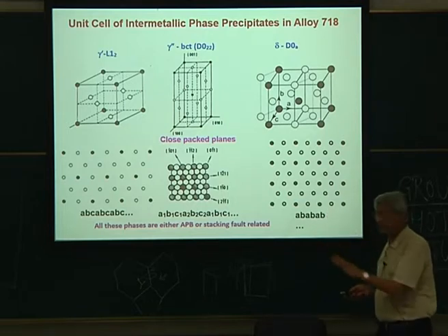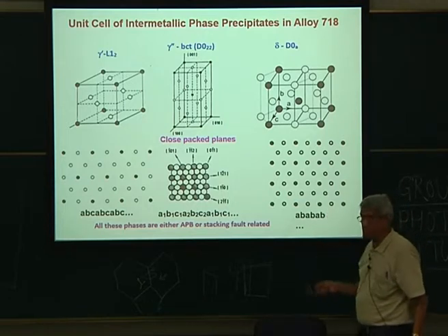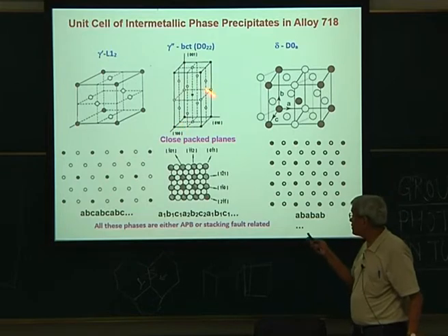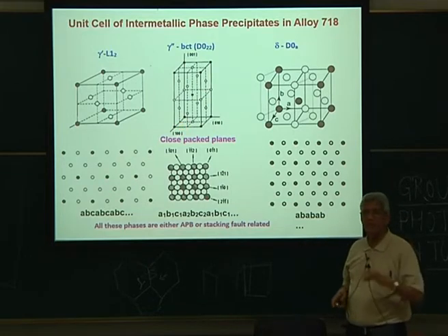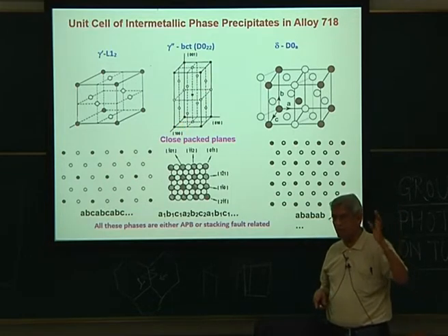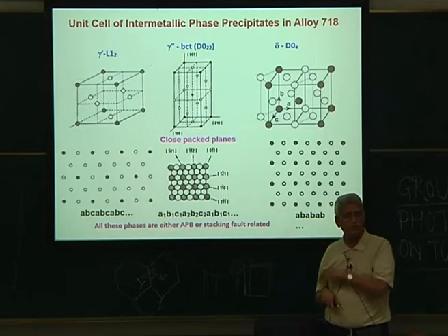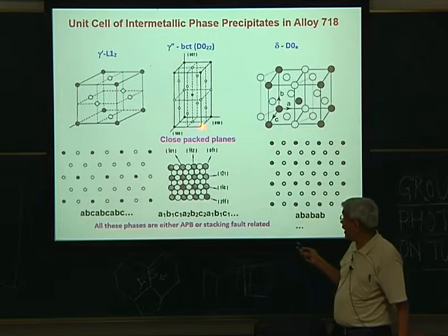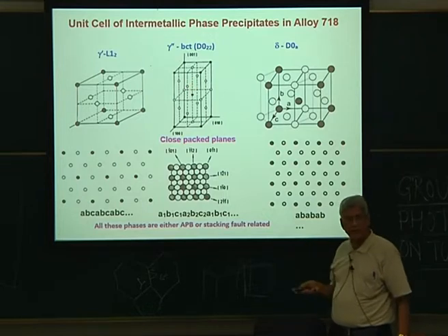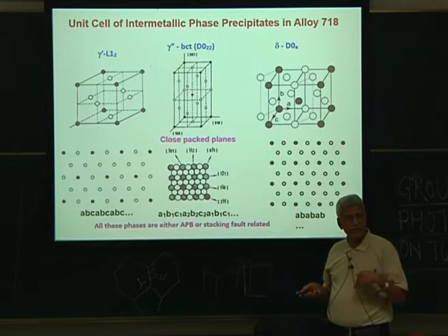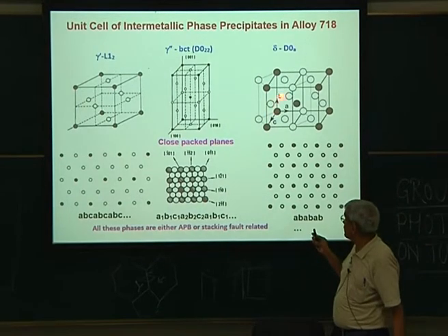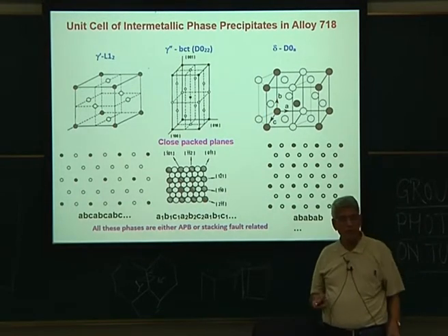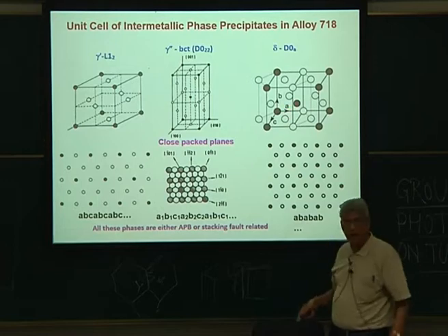I will come to this structure and explain. And this phase forms at temperatures from maybe 400 to 900 degrees centigrade. Okay. And above 900, okay, up to 1000, it's essentially the equilibrium phase which it forms. Equilibrium phase has got an orthorhombic structure.